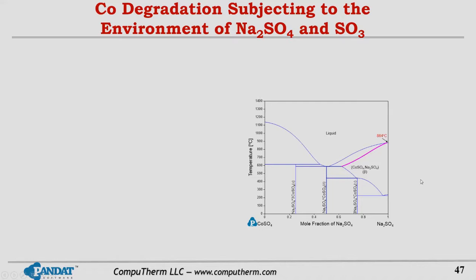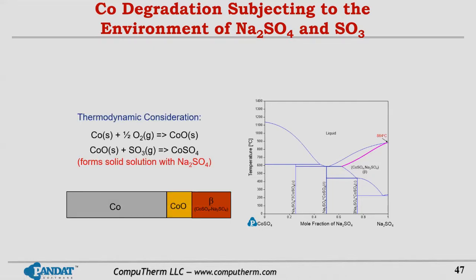So now the question is, when we use a turbine engine, right now we have cobalt. We use pure cobalt as the turbine material, and it will oxidize with oxygen to form cobalt oxide. Then with this environment containing SO3, it will form cobalt sulfate, and then cobalt sulfate with sodium sulfate forms this beta phase, the solid solution.